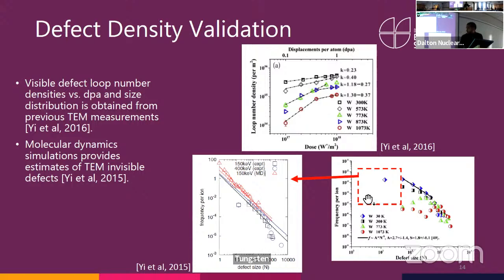And so, as Felix already mentioned, in the TEM work there is this hole for defects that are smaller than around 1.5 or 2 nanometers in diameter. We then used the molecular dynamics simulations to plug that hole and compare TGS defect density estimates to this molecular dynamics plus TEM combination, and that gave us this plot. So again, this plot is the dose and the atomic fraction of point defects. I used atomic fraction because then it's easier to compare to dPa, right? Because dPa is one displacement per atom, and atomic fraction is your damage per atom, or Frenkel pairs per atom.